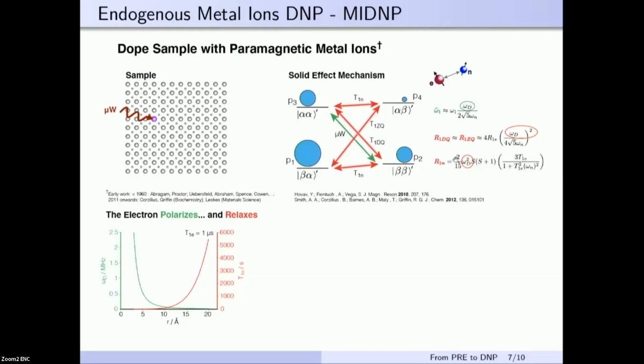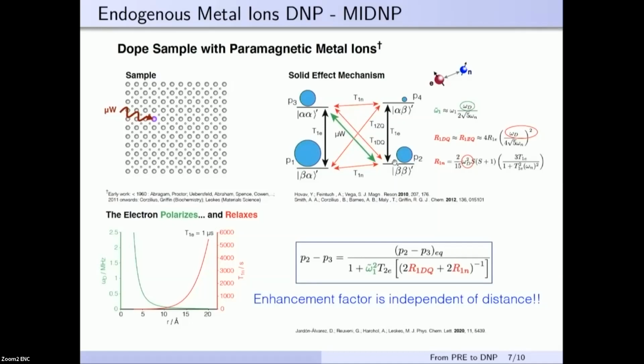So if we take all these considerations into account and we calculate the DNP enhancement, which is just proportional to the saturation efficiency of this transition, we actually find that the DNP enhancement is independent of the strength of the dipole coupling. And this result has huge impact for us, because it means that the enhancement is independent of the distance. So we can get homogeneous enhancement throughout the bulk of the entire sample. And this is the reason why this method works so well and why we are able to get DNP enhancement on very low sensitivity nuclei without the requirement of spin diffusion.